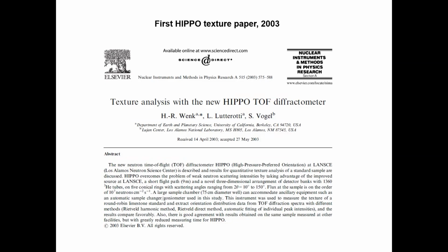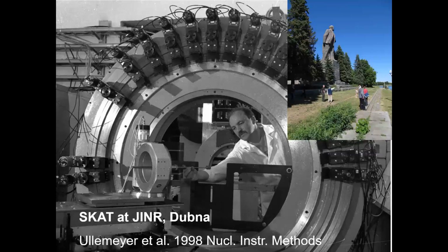2003. I should just mention this is not the only diffractometer which is largely developed, dedicated to texture analysis, and another one is SKAT at JINR in Dubna, which Ullemeyer was responsible for, that actually became finished quite a bit before HIPPO. And you see this huge ring with detectors that can actually handle samples which are up to about 5 centimeters in diameter. So it is there along the Volga and just behind the statue of Lenin.